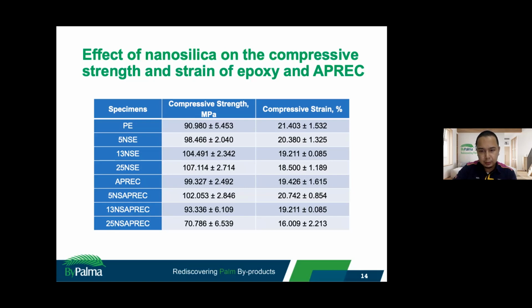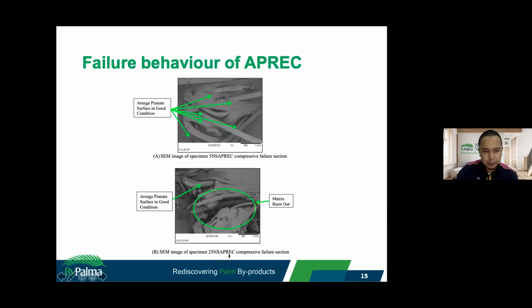So as a result, the strength of the epoxy was improved by the addition of nanosilica content from 5 to 25, and the strength of the APREC also improved until 5%. However, this reduced due to the interfacial bond of APREC. This is for 5% of APREC, and then this is for 25% of APREC.